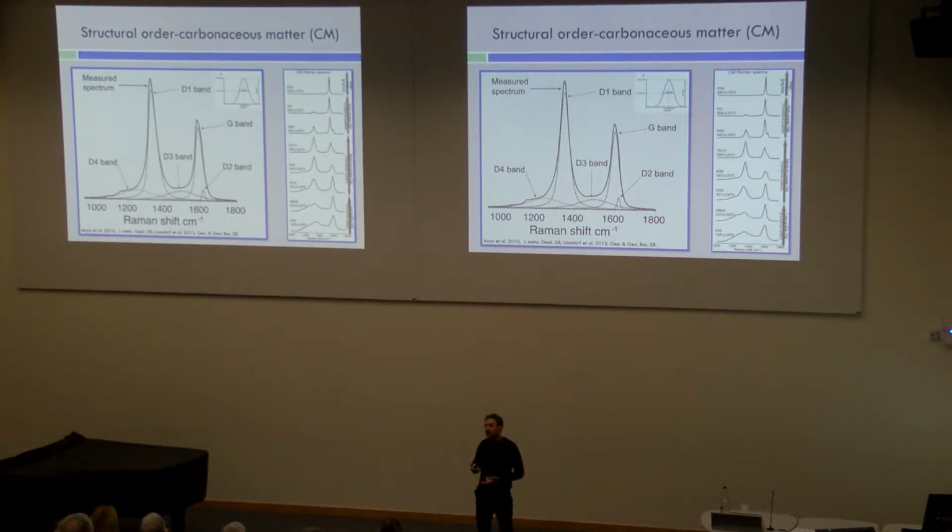Now, carbon that has been exposed to lower temperature, you'll start to see this D peak pop up, and this is the disorder peak. Now, eventually the G peak will disappear and it will become the D2 peak as it becomes more disordered, and this D peak will become shouldered by more disorder with a D3, a D4, a D5 until it becomes as convoluted